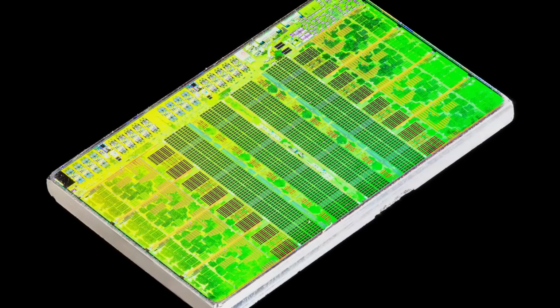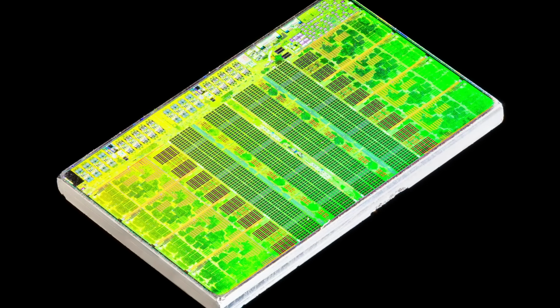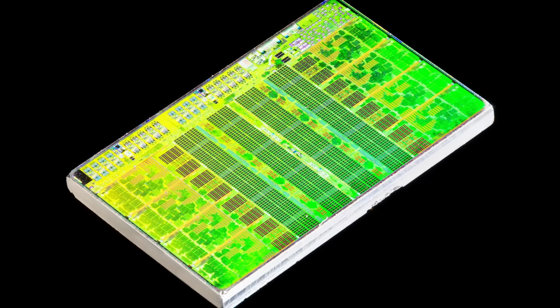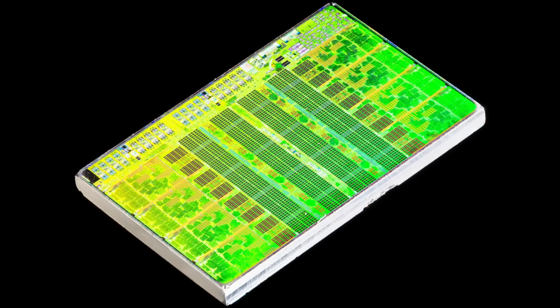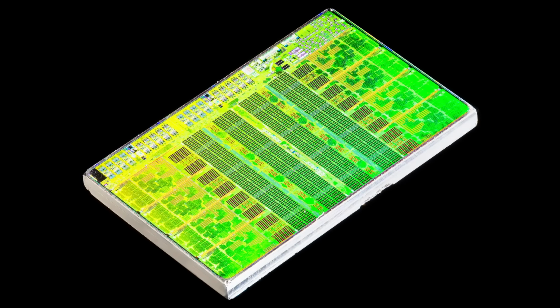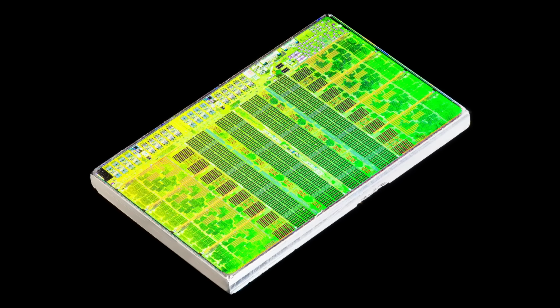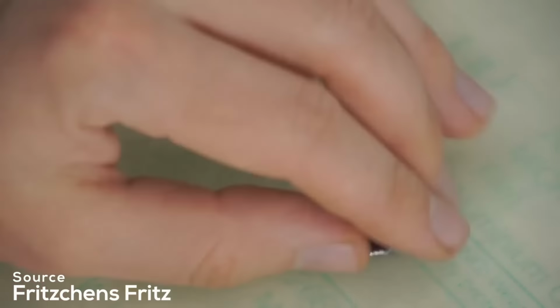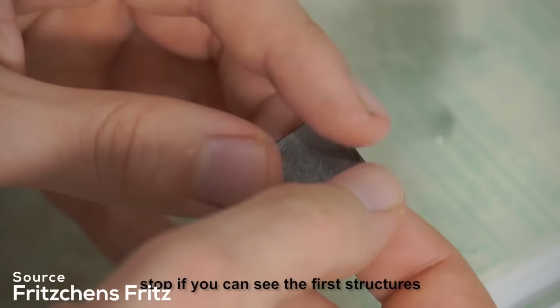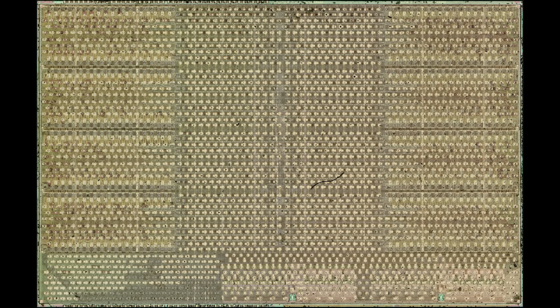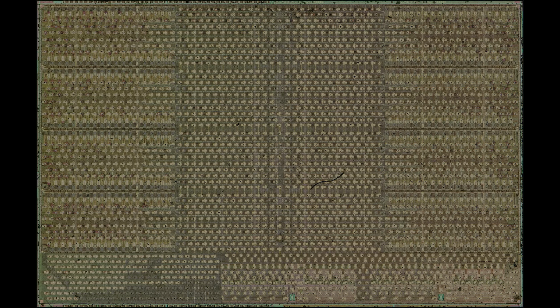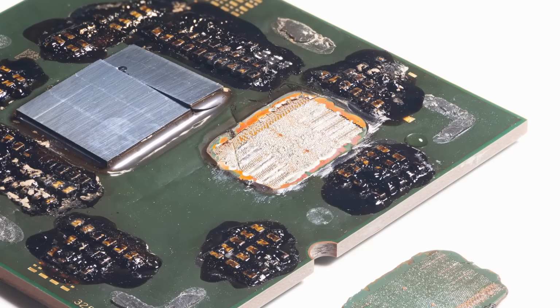Let me explain. This is a Zen 4 CCD. Right now we are looking at the side that's usually facing down towards the packaging substrate. Remember, current chips are so-called flip chips. They are placed face down. In order for us to see the Zen 4 CCD transistor structures in this picture, Fritzchens Fritz had to remove the CCD, flip it around, and grind down all the metal layers that sit on top of the transistor layer. This is how it actually looks without the metal layers removed. These metal layers are facing downwards, and then solder bumps are used to bond it to the PCB.